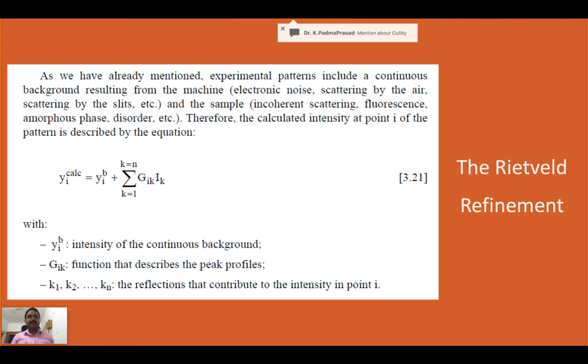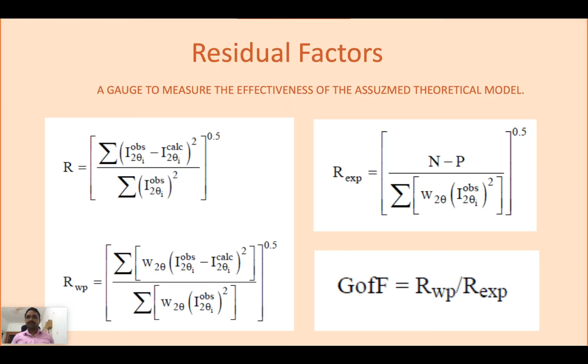For each point, we have an R value. The R value is the intensity observed minus the intensity calculated, the whole squared, divided by the intensity observed to the power 0.5. This is one type of residual factor. We call this the residual factor. In this way R values can be calculated.